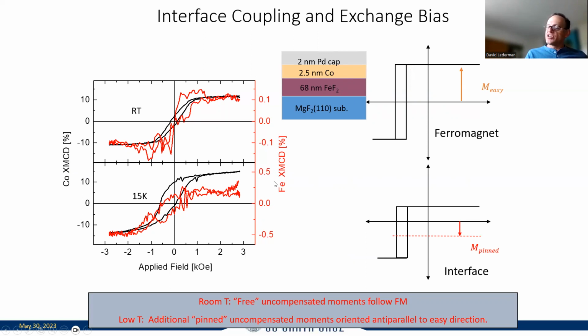This is the circular dichroism, and you can see that at room temperature you can see the hysteresis loop of the cobalt. This is the black curve here. But in addition, we were able to see that the iron from the iron fluoride had some response. It's small, but it's definitely measurable here. Then at low temperatures, this is at 15 Kelvin after field cooling, you can see the exchange bias. The loop from the circular dichroism in the cobalt has moved to the left. In addition, there is a circular dichroism due to the iron, and the entire thing is shifted downwards in signal. That means you have some pinned ferromagnetic moments in addition to unpinned ferromagnetic moments in the antiferromagnet itself.